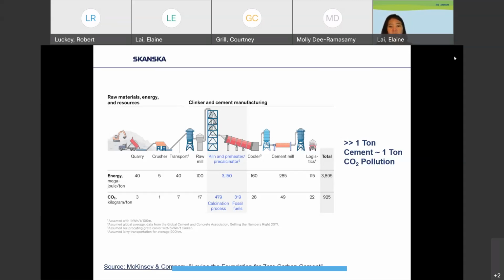So the short story here is that anything that can be done to reduce the cement content of concrete goes very far in reducing carbon pollution of concrete mixes. The general rule of thumb we use is that for every ton of cement, approximately 1 ton of carbon pollution is emitted. On average, about 7 to 15% of concrete is made of cement.